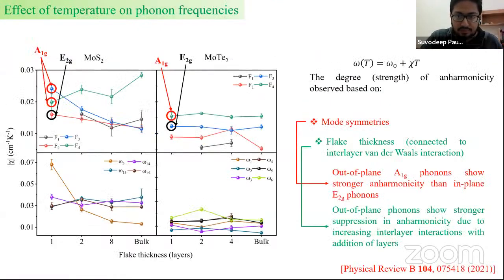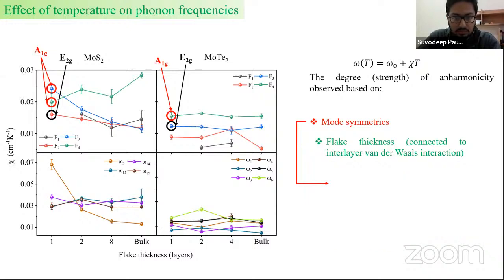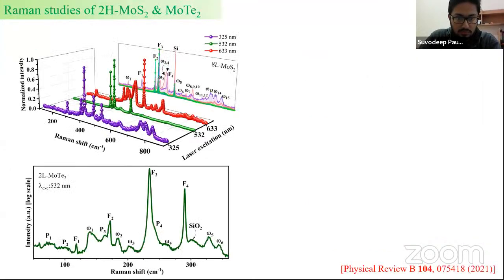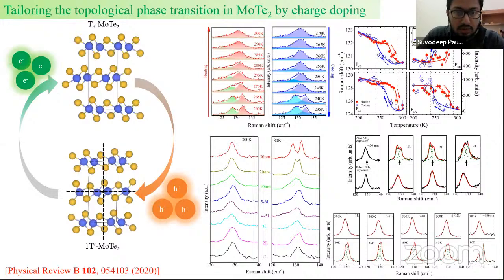Regarding the 1T prime phase of MoTe2, after 120 Kelvin there should be a transition from a monoclinic to an orthorhombic phase, from 1T prime to Td, right? It happens around 250 Kelvin. Actually, there is a paper which reports this for 1T prime MoTe2 superconducting. They say that the temperature is 120. Anyway, it doesn't matter.